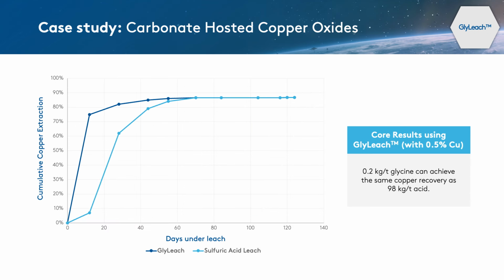If we do the acid curing before the test, we could increase the extraction of both copper and cobalt. The next example is related to carbonate-hosted copper oxide. In this graph, you can see that the y-axis shows cumulative copper extraction and the x-axis shows days under leach. The dark blue one shows GlyLeach and the light blue one shows sulfuric acid leach. This specific ore type has 0.5% copper. As you can see, after around 120 days of leaching, both GlyLeach and sulfuric acid reach the same copper extraction, around 80%. However, for the acid test, we used 98 kilograms per ton of acid, but for the glycine, we only used 0.2 kilograms per ton of glycine. So obviously, we can reduce the amount of chemicals.